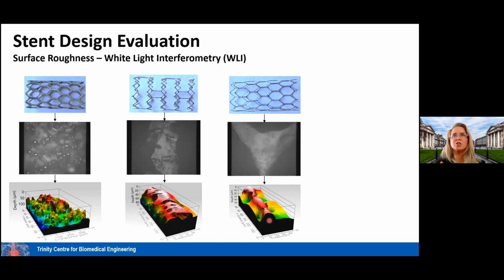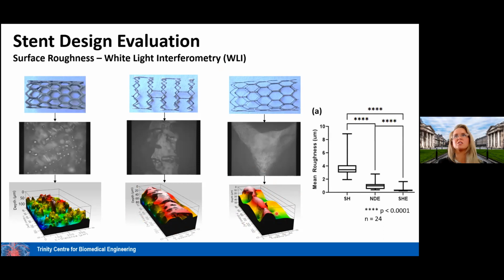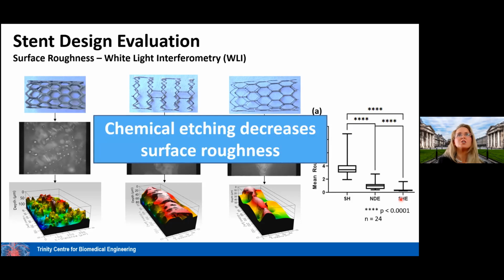And here you can see when we do etch for longer, those thinner struts result and we get a very good surface finish. And some of those metrics there, you can see our mean roughness is down at the order of only less than a micron when we etch for that simple honeycomb etch to get down to strut sizes of around 120 to 150 microns, which again would be typical of more suitable from a commercial point of view or from a real application point of view. That's the kind of strut sizes we want. So chemical etching can definitely reduce surface roughness and makes these more suitable for implantation.